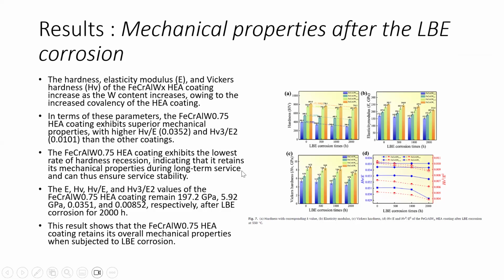So the material coating exhibits the lowest ratio of hardness decline, indicating that it retains its mechanical properties during the long-time corrosion, thus ensuring surface stability. The E, H, H/E, and H cubed over E squared values of the material coatings remain at 197.2 GPa, 5.92 GPa, 0.0351, and 0.00852 respectively after corrosion for 2000 hours. This result shows the material coating retains most of its overall mechanical properties when subjected to LBE corrosion.